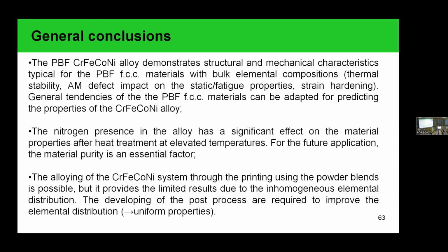but we observed a challenge that, due to this chemical inhomogeneity and the specifics of this composition, several phases form, and it limits further application, demonstrating lower mechanical characteristics than for conventionally produced materials. So it is also a challenge which should be solved in the future.